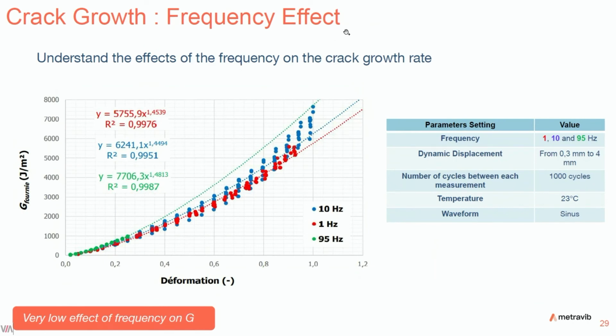What about the frequency effect? Let's see the effect of the frequency on the crack growth rate. First observation, we have a very low effect of frequency on the tearing energy, G. Here you have 3 curves, 3 different colors, 3 different frequencies: 1 Hertz in red, 10 Hertz in blue, and 95 Hertz in green. The curves are really close for the same condition, so very low effect of frequency on G.